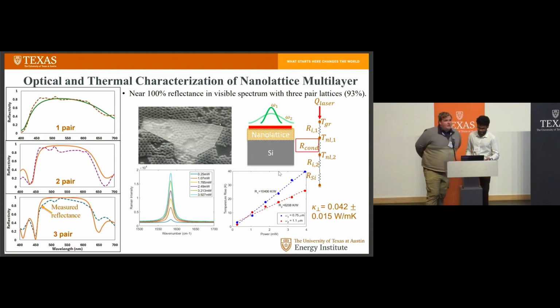So I'm in charge of thermal characterization. Typically with these small features, standard thermal characterization techniques such as TDTR, laser flash, or the hot plate method can't really apply here. So we're developing a new technique to measure the thermal conductivity. Here we utilize Raman thermometry. There are different materials which provide a Raman signal based upon their lattice vibrations. And based on the features of that signal, we can extract an effective temperature of the object we are probing. So in our case, we deposit a graphite flake, which you can see in the center image over here, on top of the nanolattice.